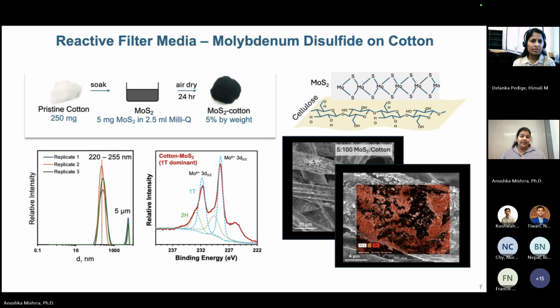And like I said, there is more scope of research to examine how we can have a complete coverage and yet not lose a lot of MOS2 due to overloading. Like we can prevent that. So through these characterization techniques, we were able to come up with a media that has the right percent of MOS2 that we need, that really worked for us, and how we can prevent a lot of MOS2 loss just by flushing the cotton surface.